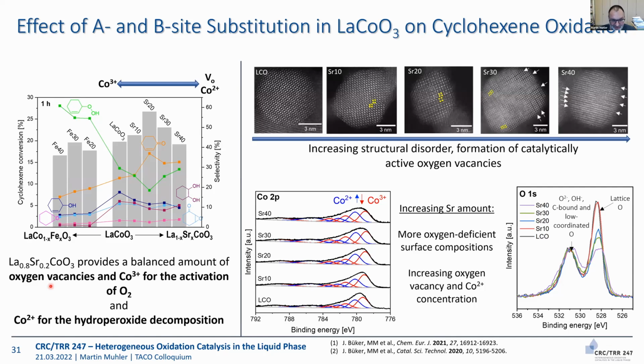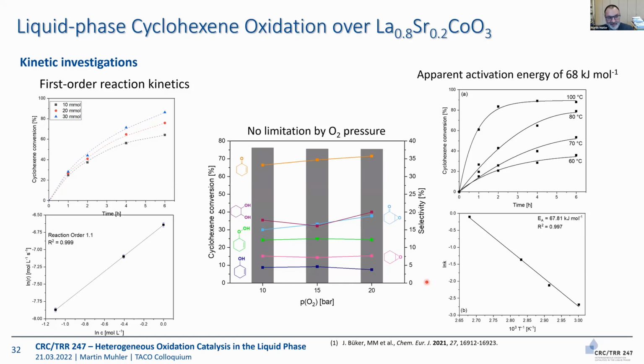From a characterization point of view, that is pretty challenging. What we see with TEM is that when we increase the strontium content, we get more and more disorder, stacking faults. XPS tells us indeed we get more cobalt 2+, and counting oxygen vacancies would be a talk in itself. That is still an unsolved problem. And when we take the best catalyst with 0.2 strontium in it, then we can perform formal kinetics, as in spite of the very complex reaction network, we can identify first order reaction kinetics.